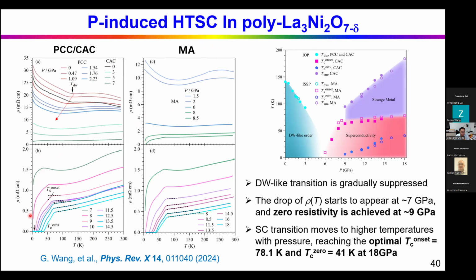And the superconducting transition moves to higher temperatures with increasing pressure. We measured up to the highest pressure of about 18 gigapascal. The zero resistivity temperature, TC0, can reach about 40 Kelvin here, and the onset temperature is about 78 Kelvin. And in the normal state, it shows this kind of linear in temperature behavior, called strange metal behavior. Based on this resistivity result, we can construct this phase diagram.